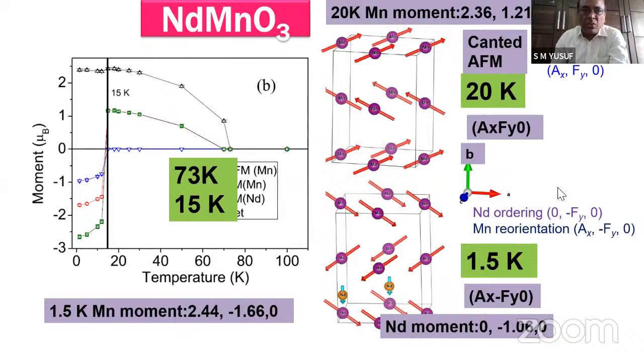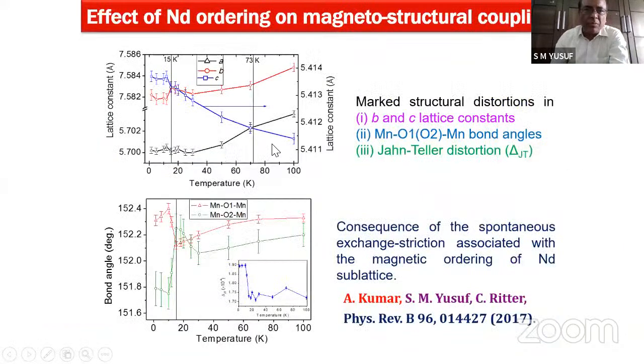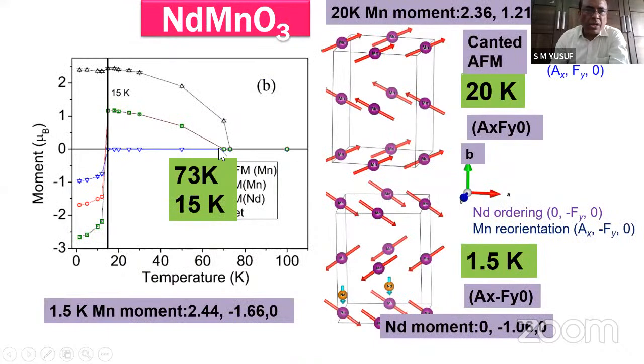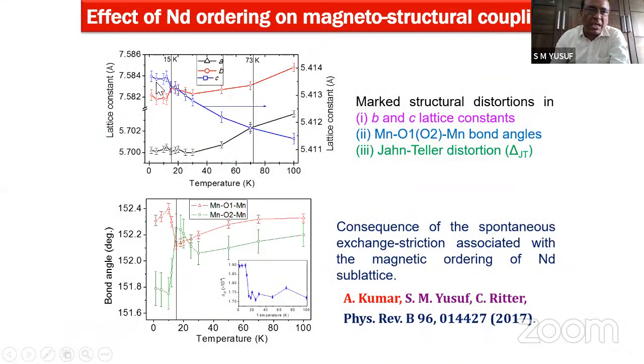When you look at the net moment, which is the green one, it shows the magnetization reversal. This is what is reflected, and the green one is the net one. Along with that, we see that there is also structural distortion taking place at the same compensation temperature, which is evident in the lattice constant as well as bond angle measurement.